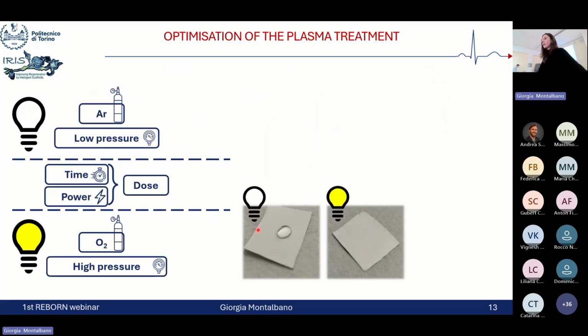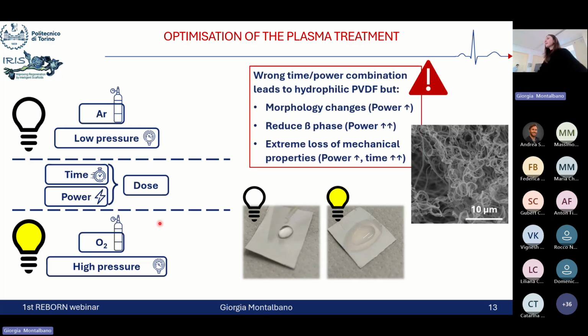So here, as we can see also from the video in the slide, this very accurate and comprehensive assessment enabled the identification of the best processing parameters, where we identified as ineffective the use of low pressure values and the use of argon alone, while the use of oxygen as a working gas and high pressure always led to a very high hydrophilicity of the surface. But unfortunately, here we need to be very careful in the optimization of the combination of the exposure time and power levels in order to avoid any modification of the morphological properties, the overall properties of the patch.